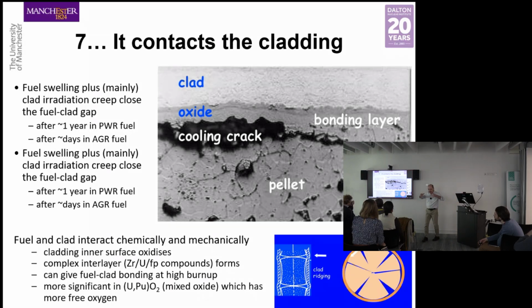Eventually, because the cladding is moving downwards and the pellet, as we've just seen, is heading in the opposite direction, that's getting bigger, eventually the two contact together and we get these bonding layers between the cladding, the metallic cladding, and the oxide fuel. What we're seeing here is a micrograph, so the fuel has been irradiated. We've taken it out of the reactor, so it's cooled. We've got shrinkage, and what we're seeing here is a cooling crack. The fuel pellet is trying to shrink back to its original dimensions. So is the cladding, but the cladding shrinks a little less, and we get this cooling crack opening up between the two.